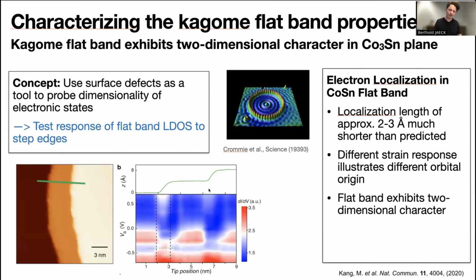On the other hand, when we now investigate the local density of states of the Kagome flatband and see how it behaves as the tip approaches such a step edge, we can see that it decays strongly. Interestingly, this is somewhat direct indication that the Kagome flatband states truly have a two-dimensional character. This is also consistent with results from ARPES measurements, which found that these flatband states show very little dispersion into the out-of-plane direction.